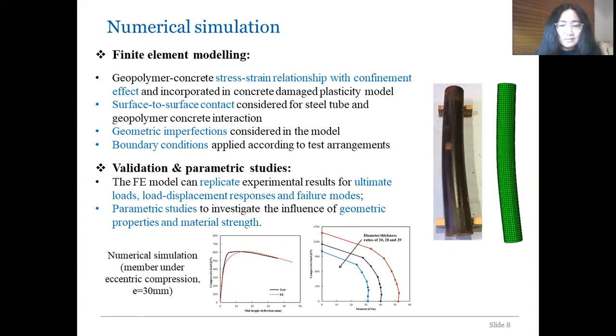So for these compression and bending curves, the pattern is very comparable to those curves of the conventional concrete filled steel tube structures. And by decreasing the diameter to thickness ratios, actually the steel ratios within the cross section increase. So higher strength contribution from the steel tube is obtained for the structures, so that higher resistance to the loads was obtained.